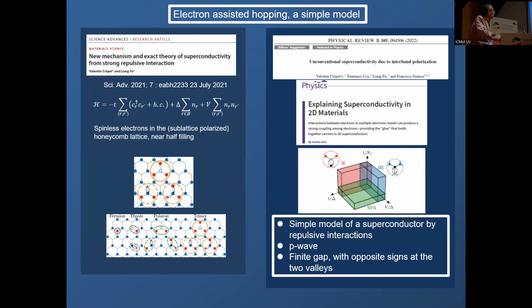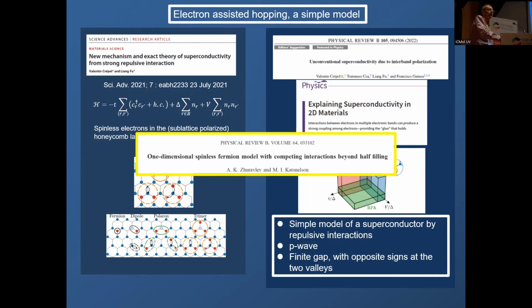We have worked on a much simpler model which shows these features, suggested by Liang Fu and Valentin Crépel at MIT. This is a kind of toy model for repulsive interactions, but which induce superconductivity because they include some kind of electron-assisted hopping. This is the simplest model you can think of. You have electrons without spin in the honeycomb lattice near half filling and with a strong potential which biases one sublattice with respect to the other. And the simplest possible interaction in such a system is a repulsion between electrons at nearest neighbor sites. Nevertheless, that's enough to give you superconductivity. My colleague Misha Katsnelson pointed out that similar systems, not quite the same, were already studied in the Soviet Union way back. I was not surprised.